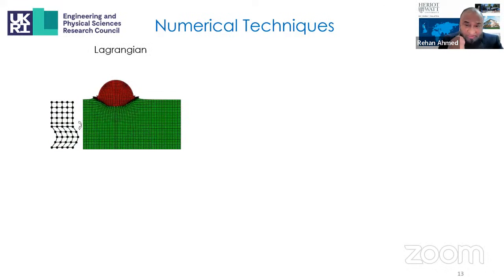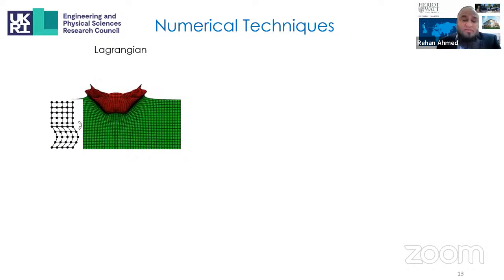So in the Lagrangian analysis, the mesh deforms to mimic the deformation of the material as shown in this slide. So here you had the original material or the original mesh, and as the mesh deforms, basically it accommodates the elastic and the plastic strain in the material. It can run into some stability issues. For example, here the aspect ratio of the elements have gone really bad, and that can lead to basically either incorrect results or the termination of the program.